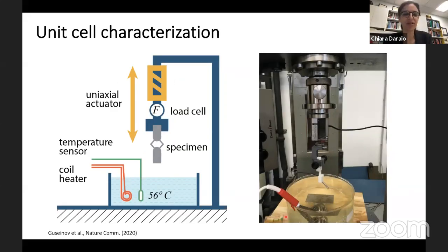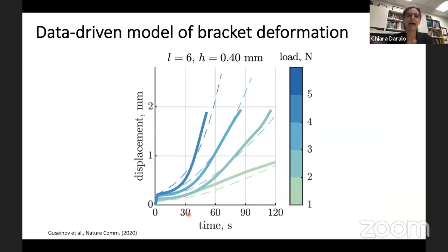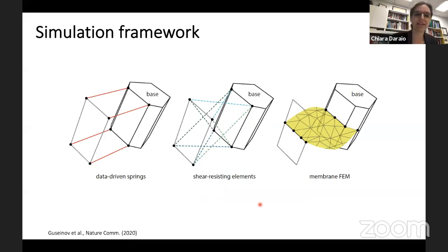But how do we know how fast and how strong these brackets are? Well, again, we went for a data-driven campaign where the students involved in this project were effectively measuring a large number of specimens with different geometry, bracket thickness, bracket lengths, different load applied, and so on, in a bath of fixed temperature. And by collecting this data and storing a lot of these displacement-time curves of deformation at different applied loads, we could construct a data-driven model, so basically fit the experimental data to a numerical model that then was able to be fed into a simulation framework.